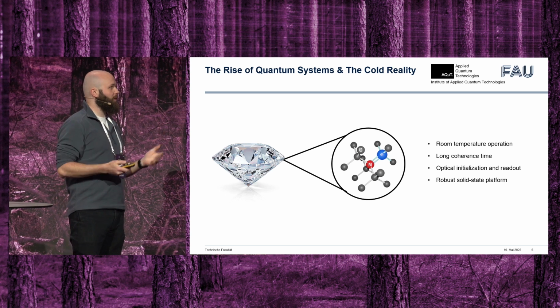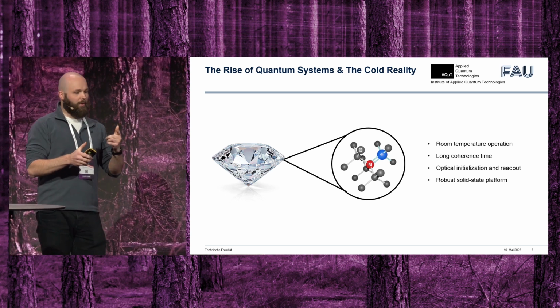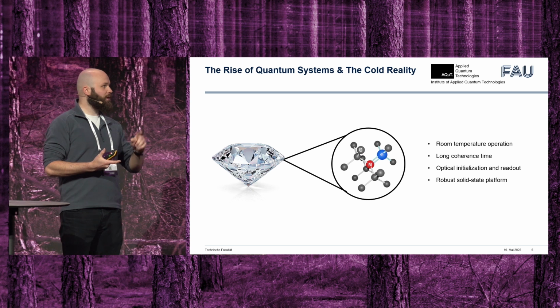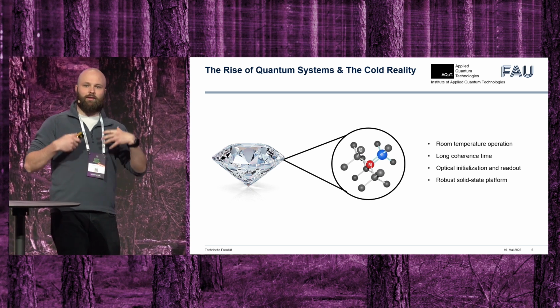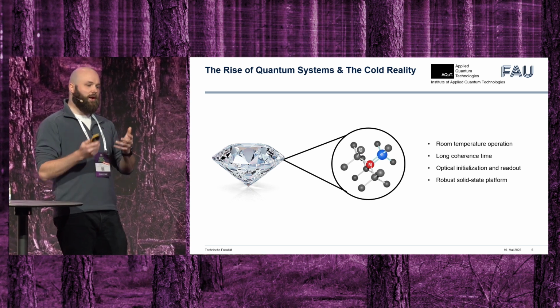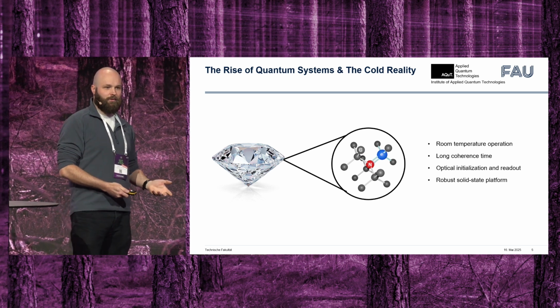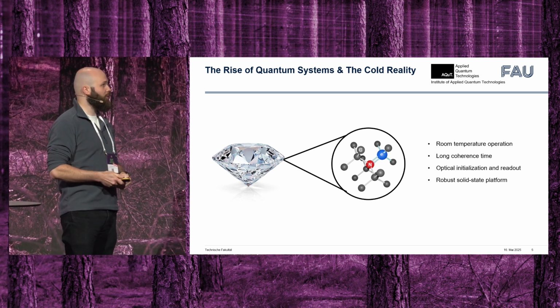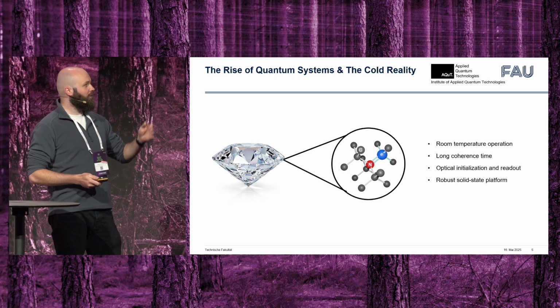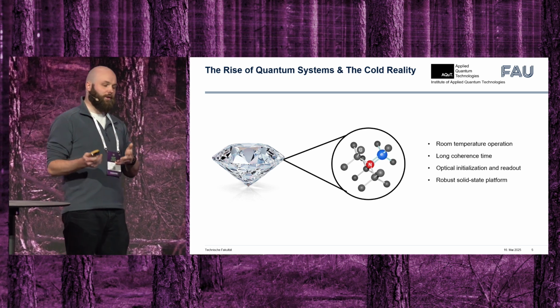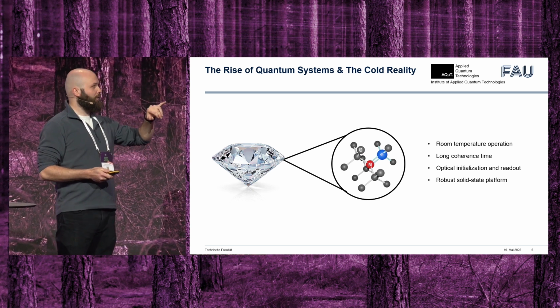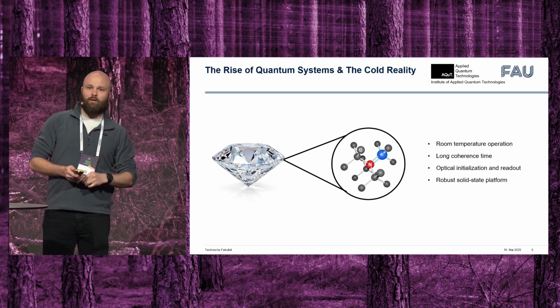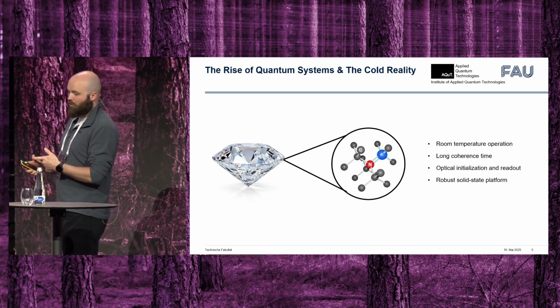And due to this nice crystal host, we are able to interact with it at room temperature. It offers long coherence times, so it can save information long enough for us to read it out. And this is practically what we abuse in this case. It is optically active. We can read it out and initialize it optically. And the diamond is a very robust solid-state host platform that is biocompatible. It does not degrade over time.